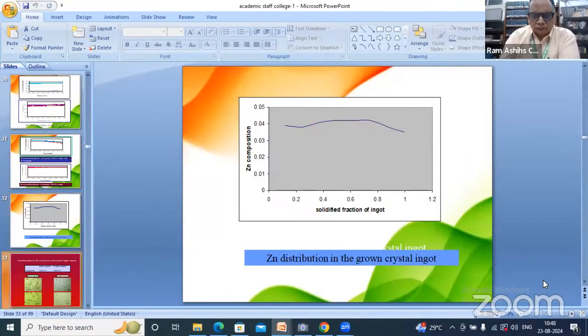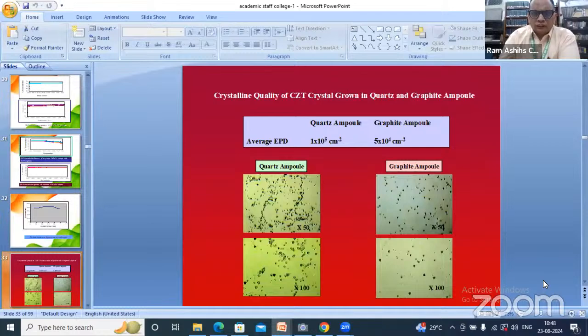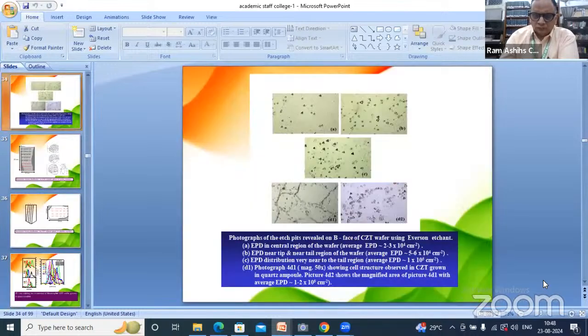This is the zinc distribution. This is the EPD, for the crystalline quality. Some cellular structure is there, and this shows the low angle grain boundaries present in the crystal. In the graphite crucible, we minimize the low angle grain boundaries. This shows the different EPD and different types of structure.